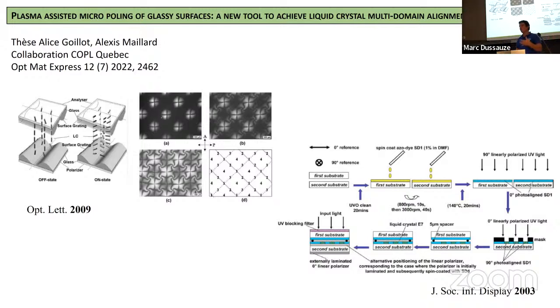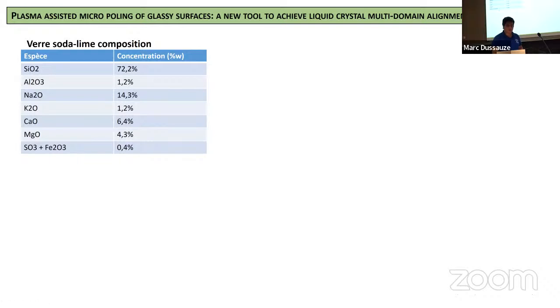So before the PhD, we were discussing what we can do with poled glasses, electric field, and liquid crystals. We would try to put liquid crystals on such kinds of glasses. That was quite interesting because there are lots of different methods in the literature. How can we control the liquid crystal alignment on the surface without using electrodes? Just by using, for example, patterned polymers or some different topology. So the idea was to work on commercial glasses, and Alice tried different kinds of poling, almost everything we can do, and that was not working very well at all.